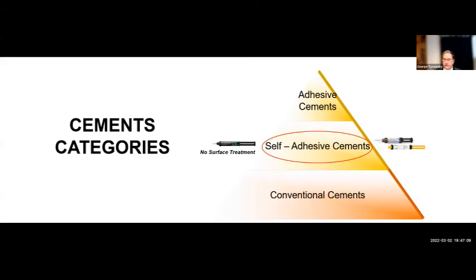On self-adhesive cements, this is becoming very popular today. It's not as strong of a bond as the adhesive. Basically, you can get 30 megapascals for the total adhesive technique. We get about 15 to 17 for self-adhesive, but the benefit is its ease of use. There's no surface treatment to the tooth structure whatsoever.